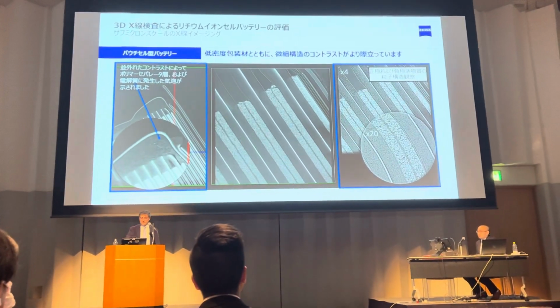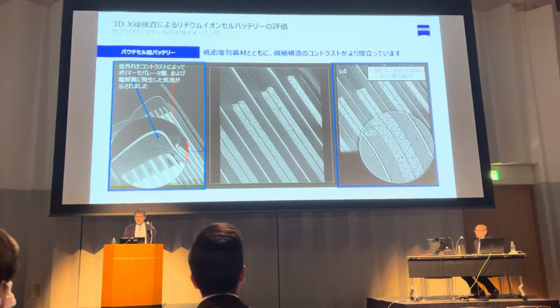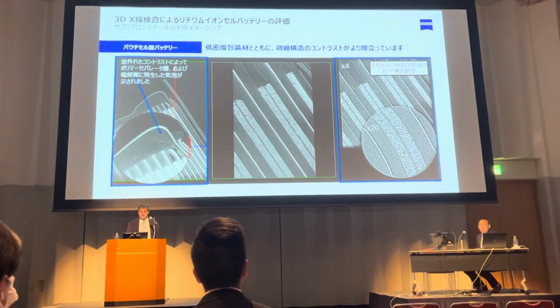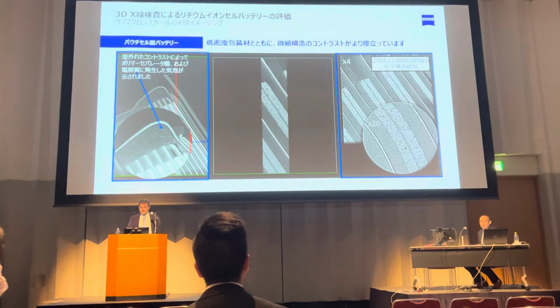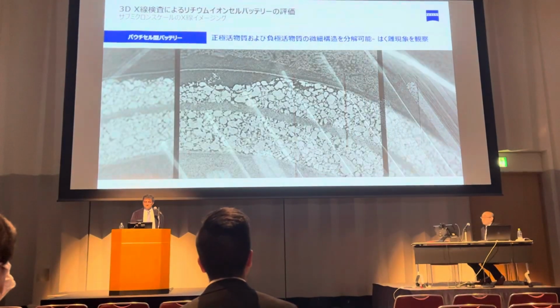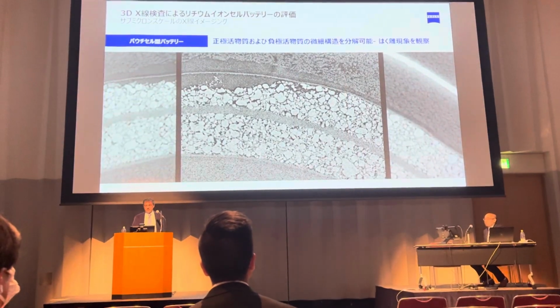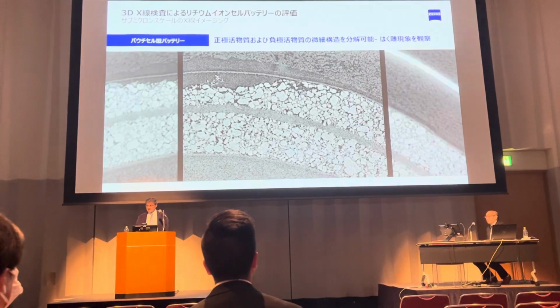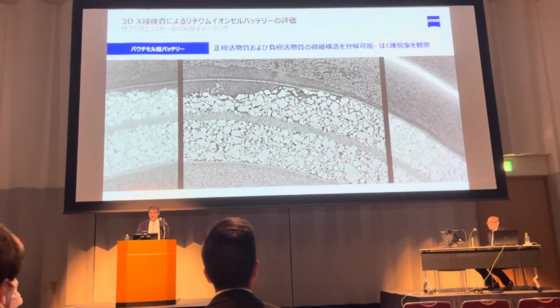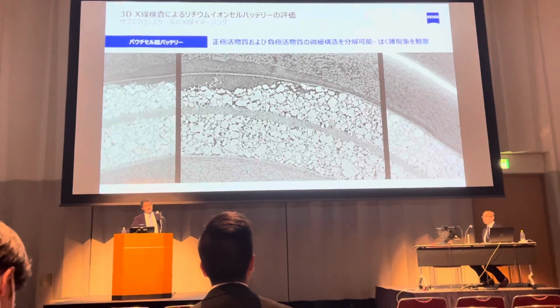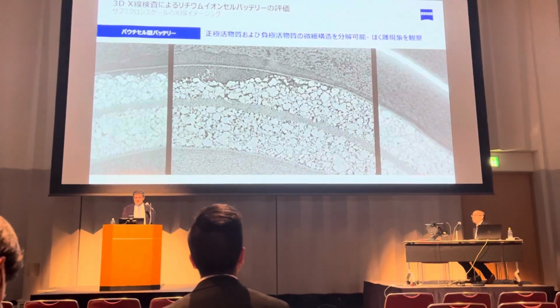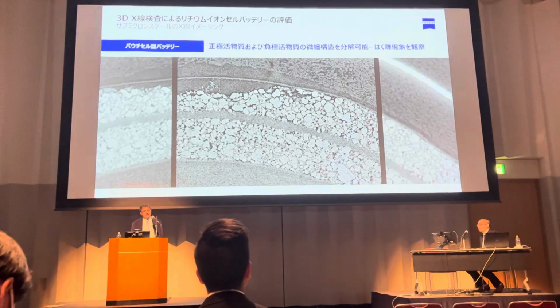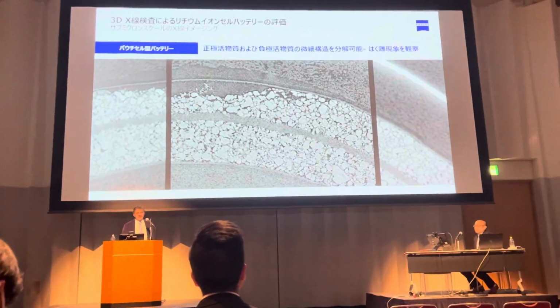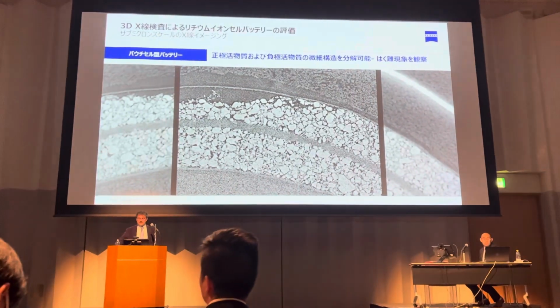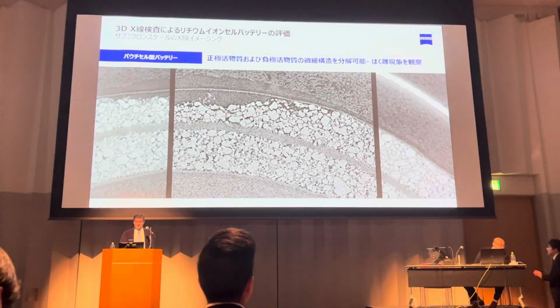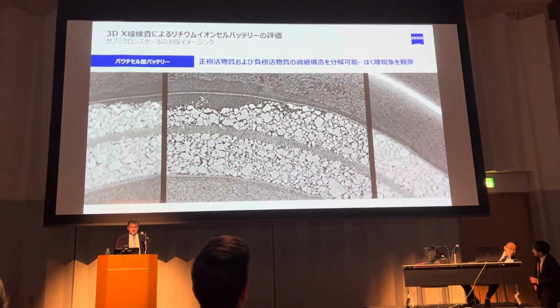And you saw passing by the traces of some voids or porosity inside of the sample and unpacking of those particles after degradation. And you can see traces of delamination and features at high resolution, as you can see here. When you increase the magnification all the way to the particle level, you can see the granularity. And again, this is acquired with X-ray. It's not an electron microscope image, so it's really great to get this 3-dimensional volume non-destructively or non-invasively.